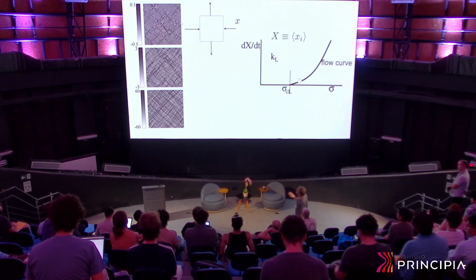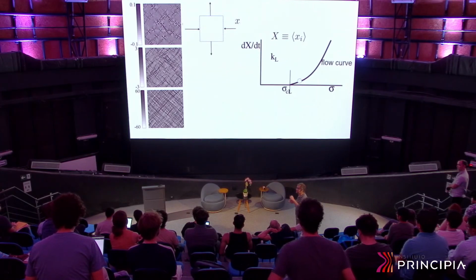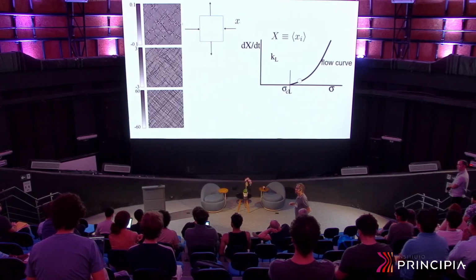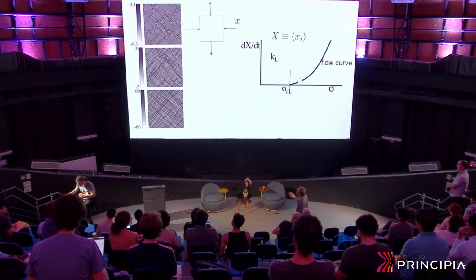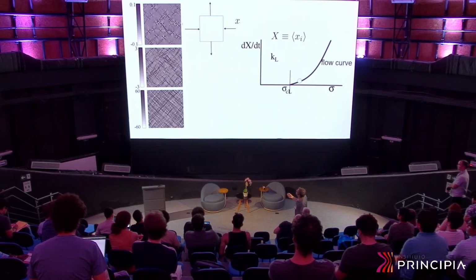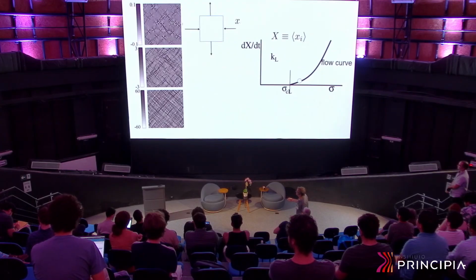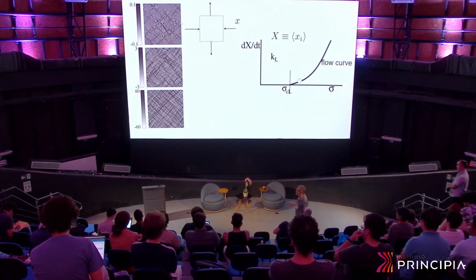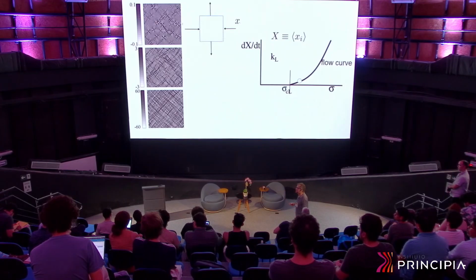Well, actually, the different color here is the strain state at different points, which is what some of these optical techniques look at when you observe with a microscope. You have to think that the level between white and black is the strain state of each point, with reference to the average strain of the sample. So white regions are less deformed than the average, and black regions are more deformed. Here you see the correlation: there are regions that are more deformed, forming kind of lines, and other regions that are less deformed. But on average, the color of these samples is the medium gray that is there. But I agree it's correlated with these images, because the microscope images in fact see the strain state of the sample.